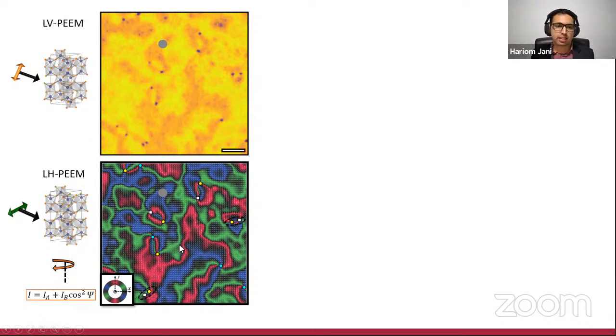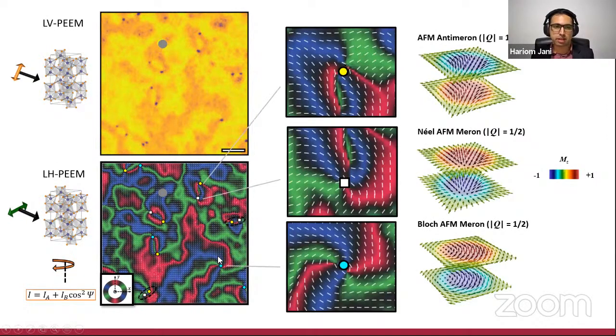Now, if we look at individual objects and zoom into some of them, let's start with the bottom one here. We actually have the Néel vector pointed out as the white dashes, and the R, G, and B colors corresponding to the in-plane phase. Now, note this is modulo 180 because this technique cannot distinguish objects which are anti-parallel to each other. But irrespective, we can very clearly note that there is some kind of winding, which actually corresponds to a Bloch AFM meron.